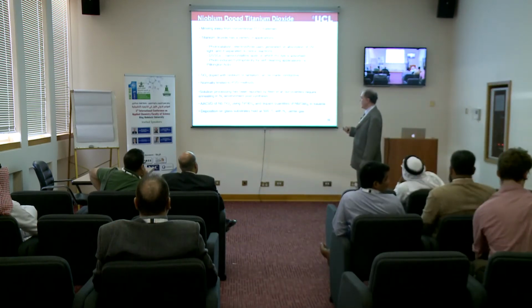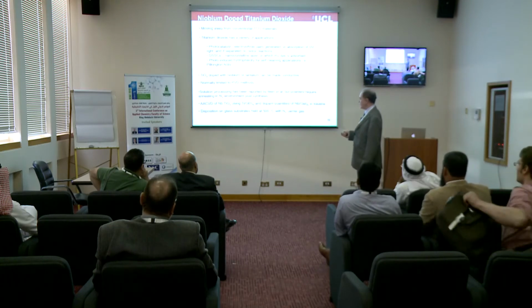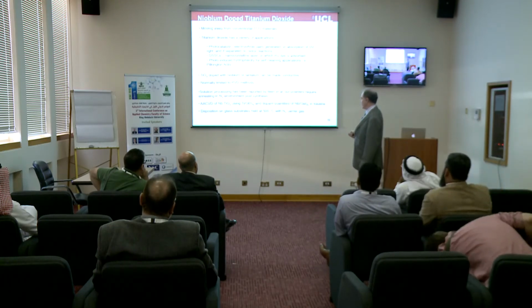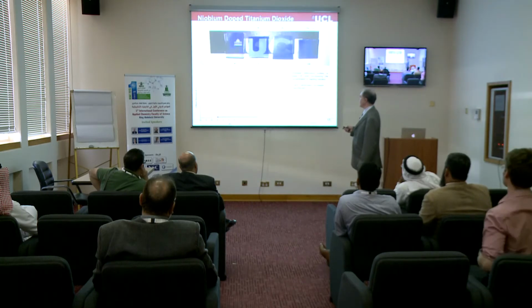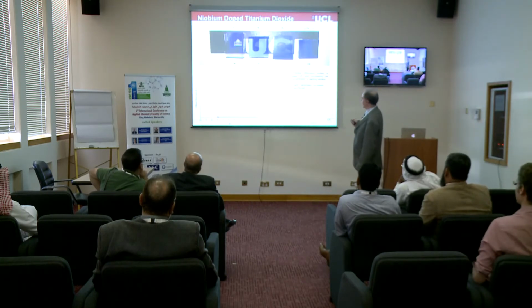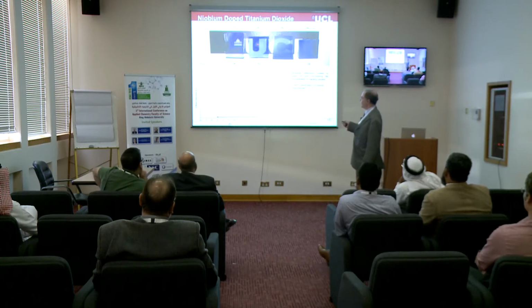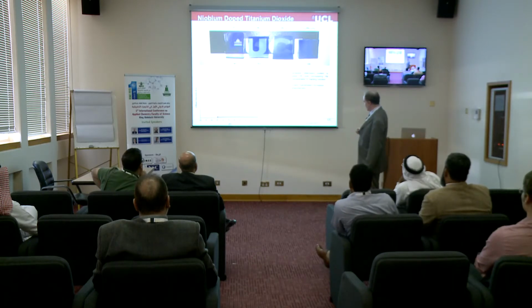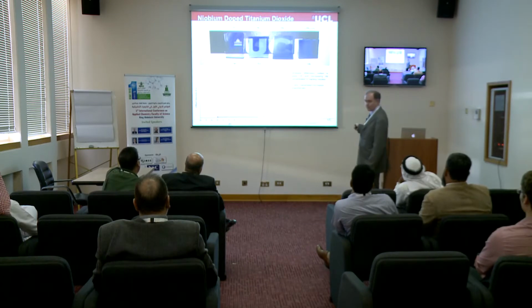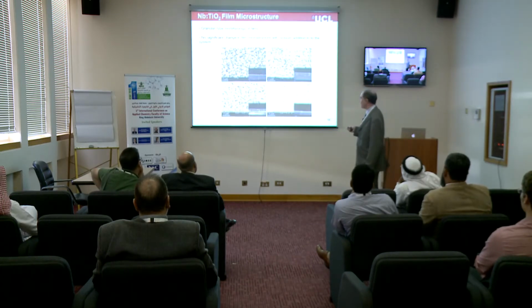And the way in which we did it is that we combined these chemicals together by aerosol-assisted CVD at around 500 degrees C. And when we do that, we've got a little subliminal message there for the university behind. Putting niobium into the lattice, we can generate this beautiful blue colour. It hasn't come out very well on this particular screen, but a beautiful blue colour where we have doped niobium into the titanium dioxide lattice. And we can see as we put niobium in, we get a Vegard's law relationship in terms of the parameters increasing.